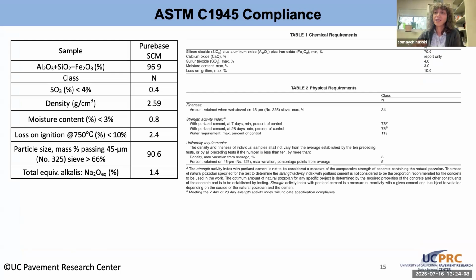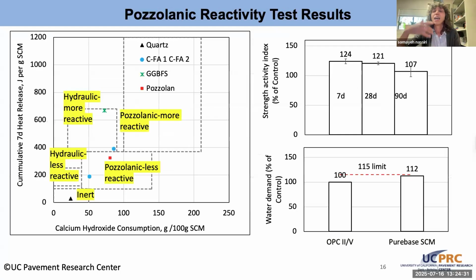They produce metakaolin mixed with a silica type SCM. It is produced locally here in California, in Ione, California. And everything started, like I said, with the characterization of the essential oxides, looking at density, moisture content, any carbon or organic matter, particle size, everything checked out. So we did the first level of screening, looking at alkalis and all of that, and progressed to looking at the results of pozzolanic reactivity.